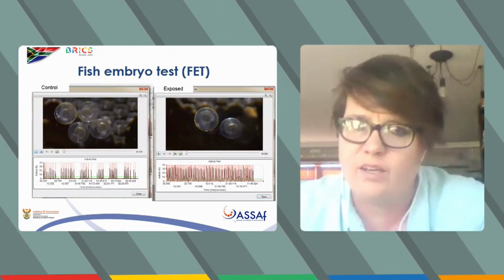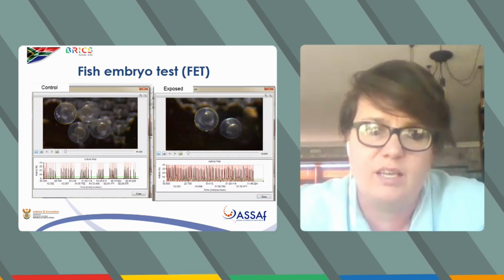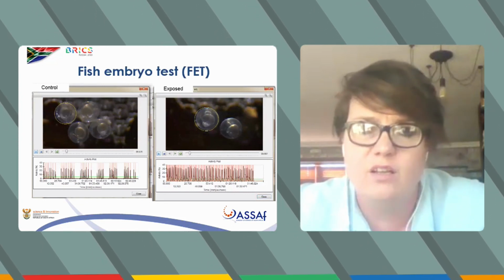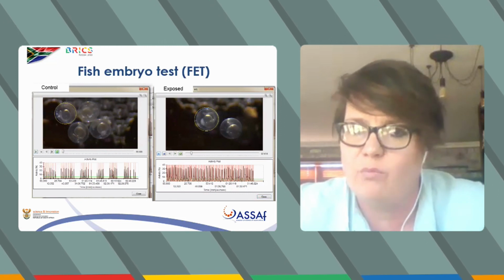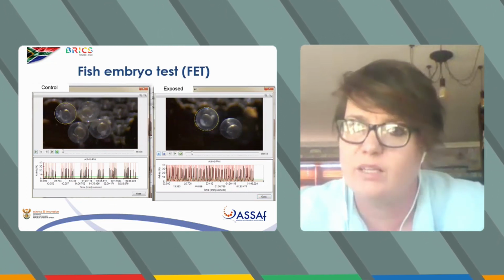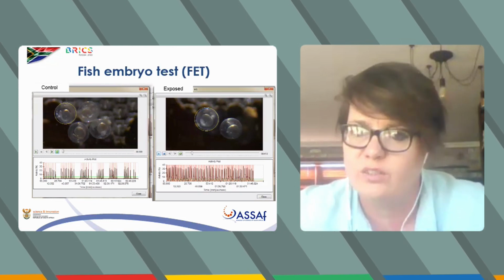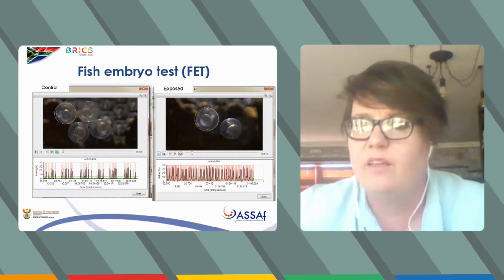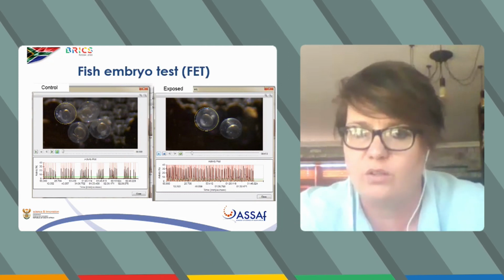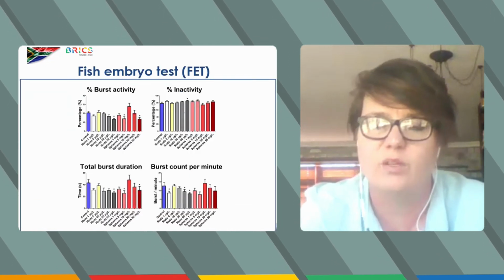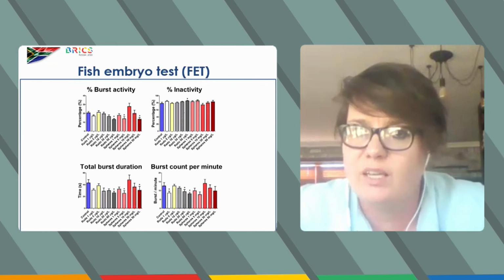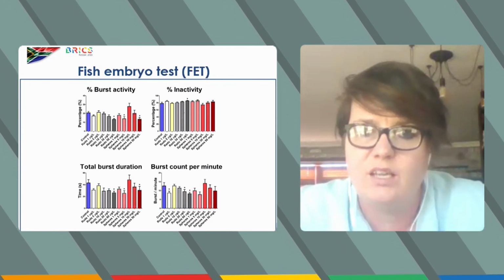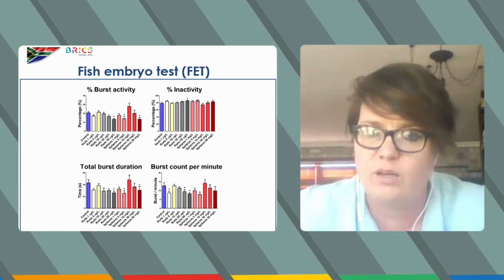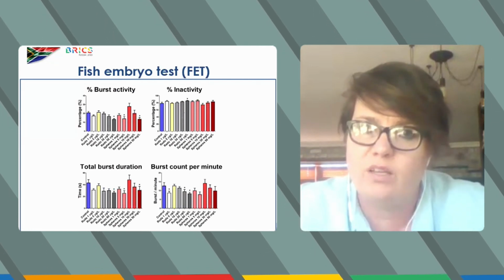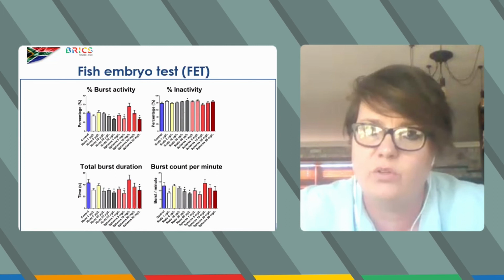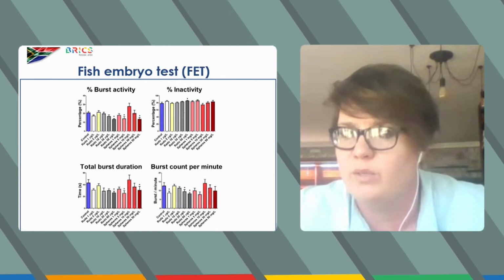So if we look at the actual videos in front of you, you can see how we would measure this activity. So this is physical activity of an embryo, and you would want an embryo to have some activity, but not to overexert itself. If it overexerts itself, then you would have a decrease in the actual growth potential of the organism. So what we then measure is burst activity, percentage inactivity, and your total burst duration, as well as counts per minute. What we found is there was a decrease in the percentage burst activity across both groups of material.